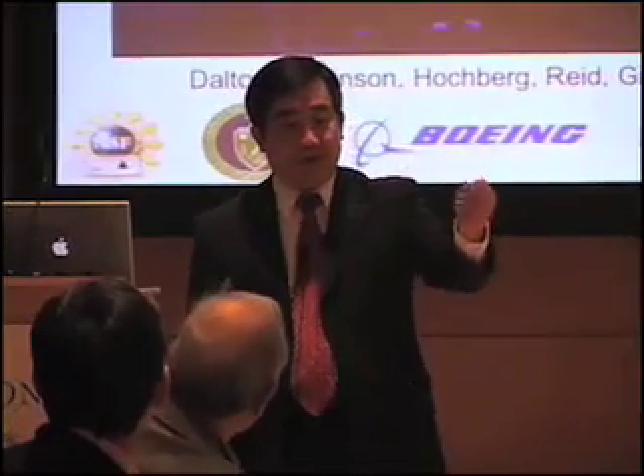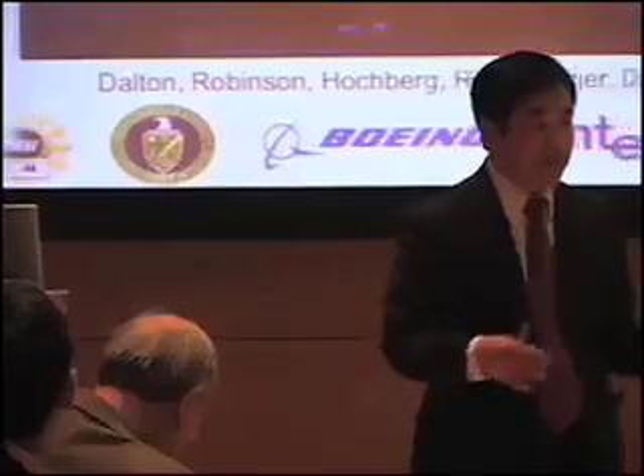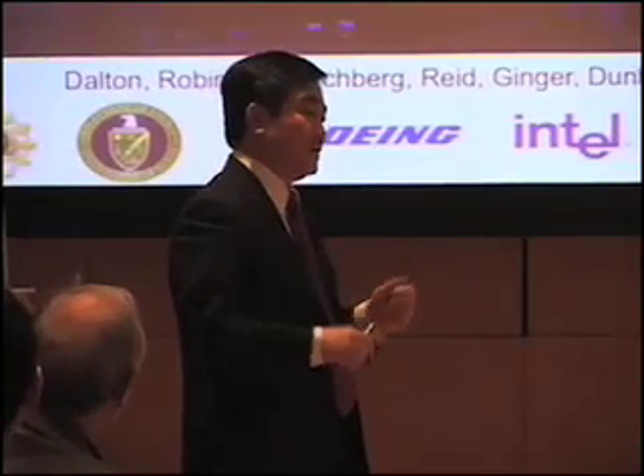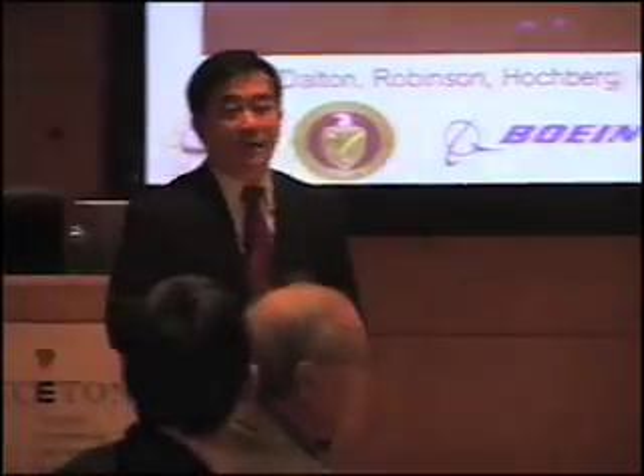So if you look at why OLEDs haven't been commercialized, because you make an active matrix, after you run it for a while, the blue will selectively fade away. It only lasts for maybe say 10,000 hours. But the efficiency for blue OLED, I think, is lower than gallium nitride LEDs. Typically for blue LED, you can get about 20 to 25 candela per amp, but I think gallium nitride is significantly higher than that.